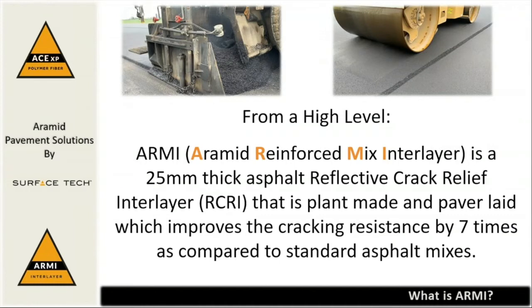When you're looking at an overlay on a concrete or a thick asphalt pavement, one of the biggest concerns is the continual movement of the joints or deep cracks. Simply paving over the joints or cracks without accounting for this movement will result in an overlay that will crack within a very short period of time, sometimes within months. ARMI, Aramid Reinforced Mix Interlayer, is a thin paver-laid fine aggregate asphalt mix that produces a very crack-resistant interlayer that is used to construct asphalt overlays on concrete pavements and deep asphalt pavements.